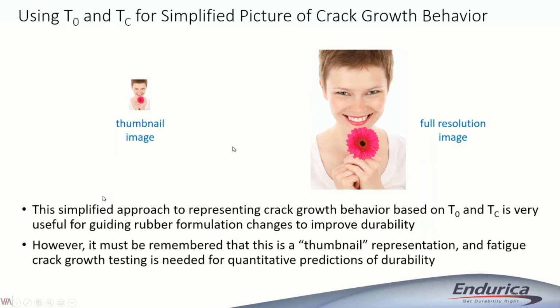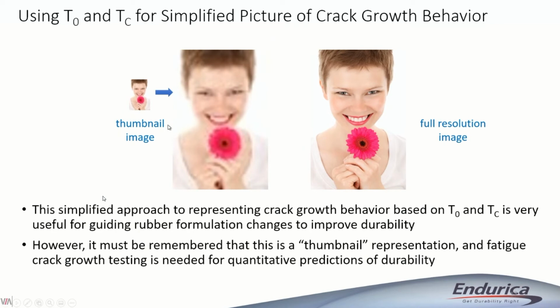So the practice that we recommend is you should think of this intrinsic strength as a low resolution version of the crack growth rate curve. If you measure T0 and TC, that puts you in a position to get a rough picture of things. Now, if you want the detailed picture that you would use in a full, deep, safe life approach analysis, then you're going to use a fatigue crack growth test system. But if you just want to do compounding type studies, low resolution sometimes is enough.